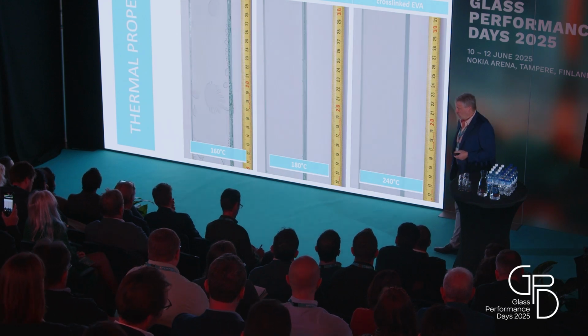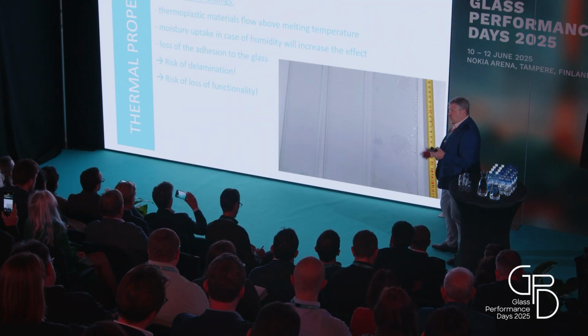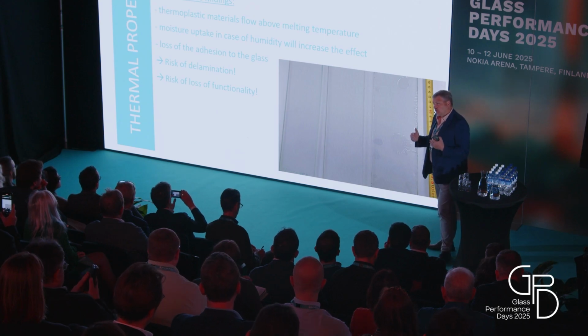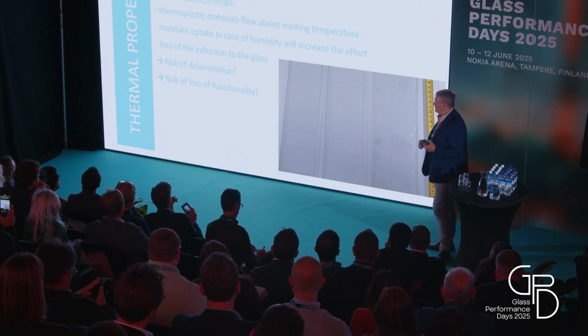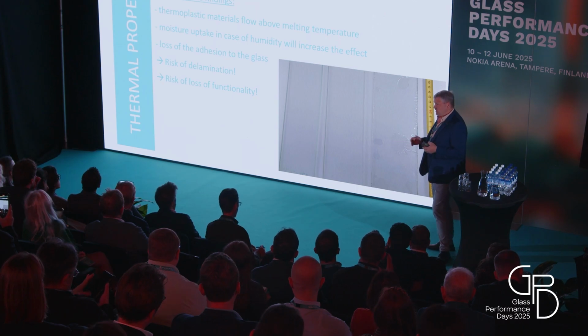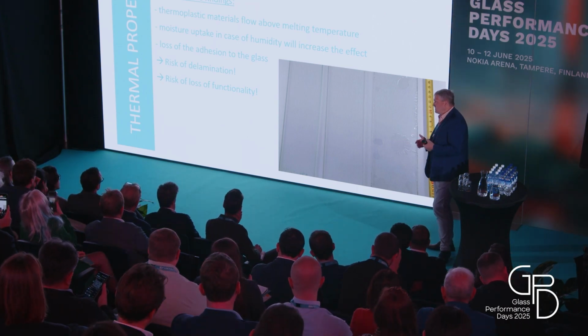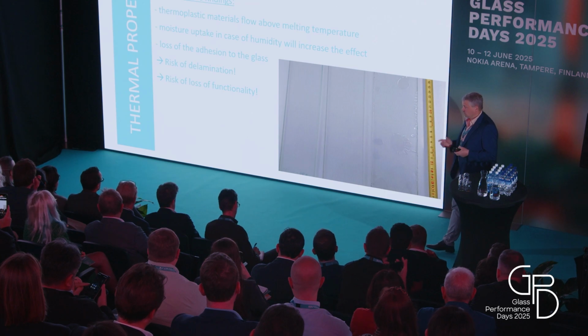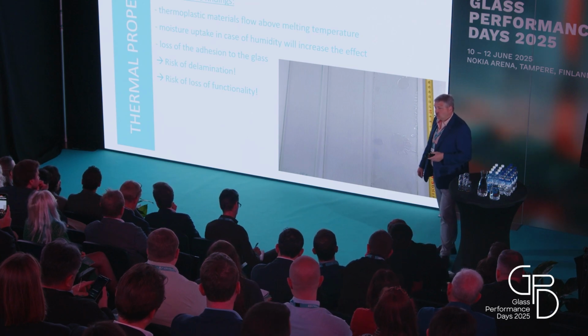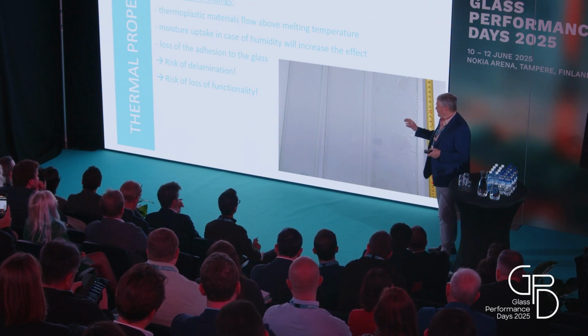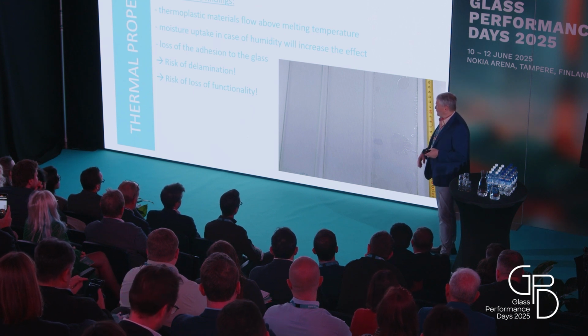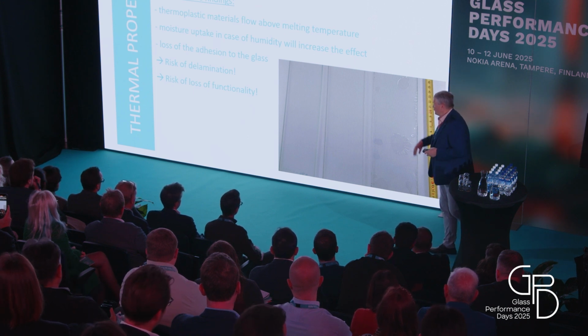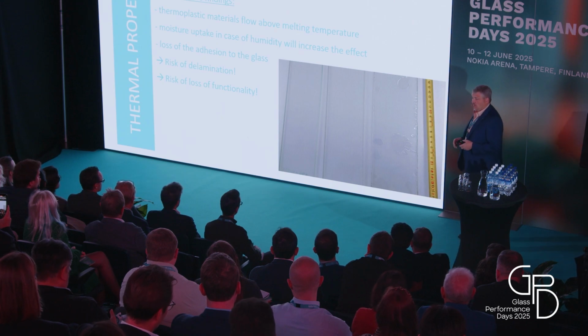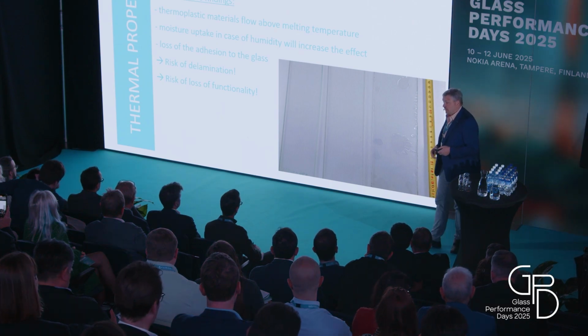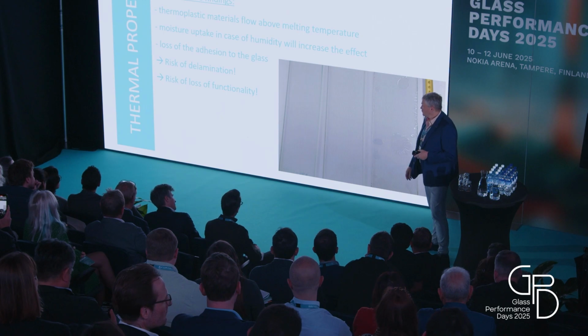The reason for this finding is, of course, as I said, thermoplastic materials will flow at a temperature above the melting temperature. This can be increased or also influenced by humidity and moisture uptake of these films, and this will form bubbles, as you can see here. This leads to loss of the adhesion to the glass, and finally to risk of delamination and, of course, loss of functionality.